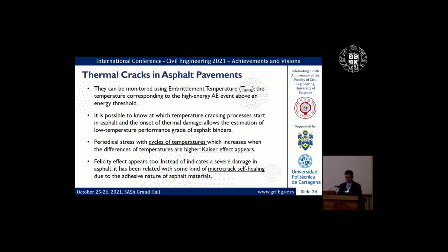If you have a periodical thermal load with different cycles of temperature, it has been found that the Kaiser effect that we have seen before is happening here too. So if the difference of temperatures doesn't change, you are not going to get any acoustic emission. But if the temperatures rise, or the difference of temperatures rises, then the acoustic emission will be measured. And also the Felicity effect, and this is something interesting, has been found here,